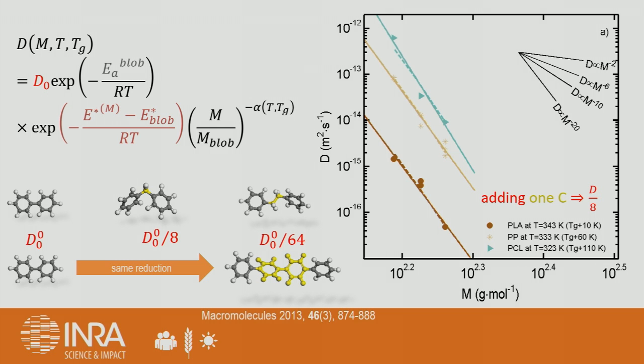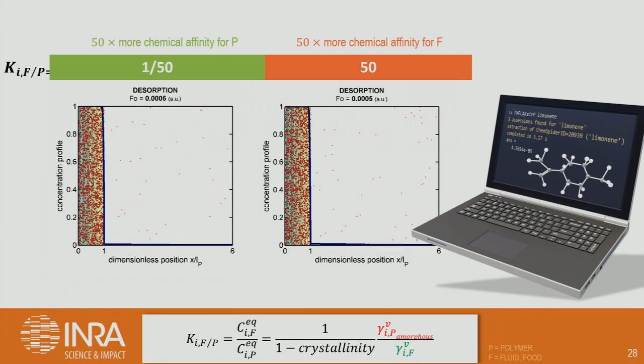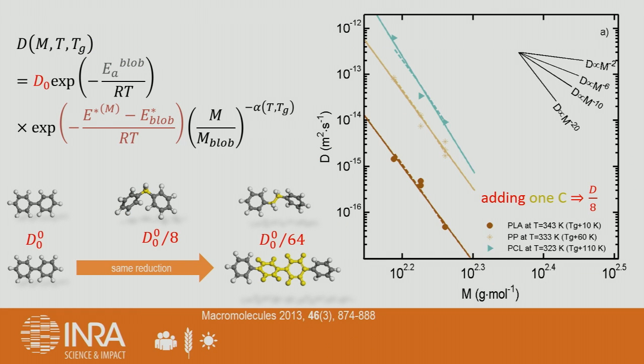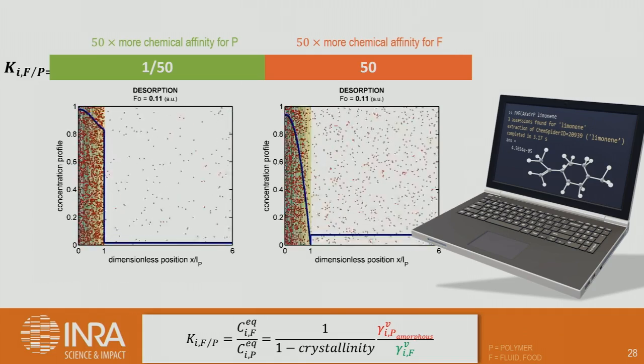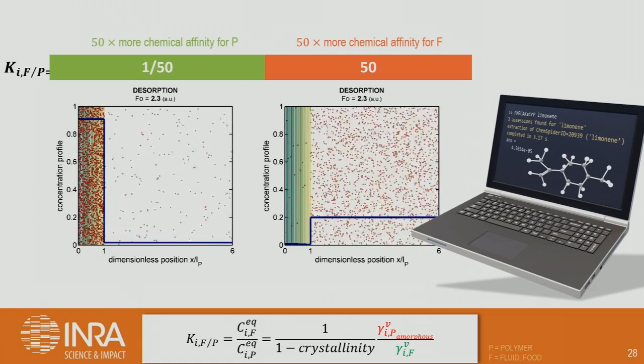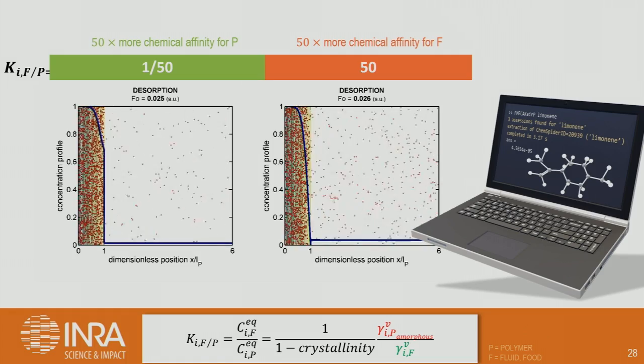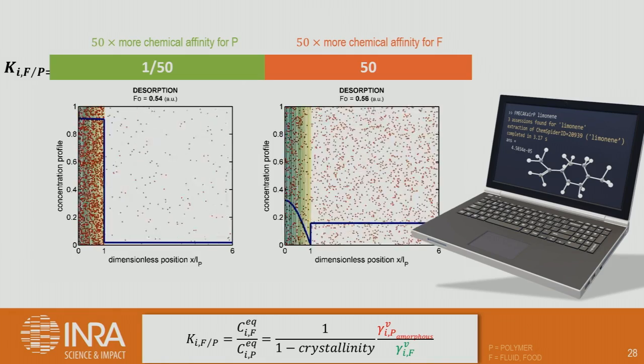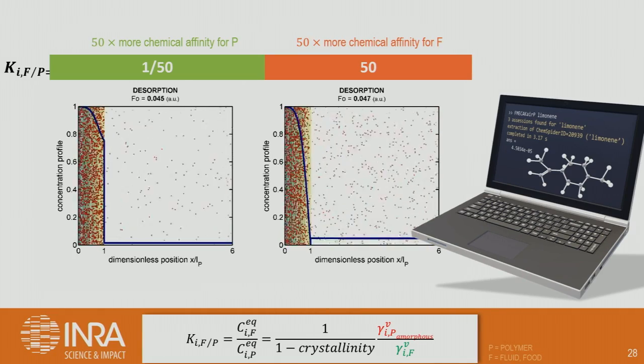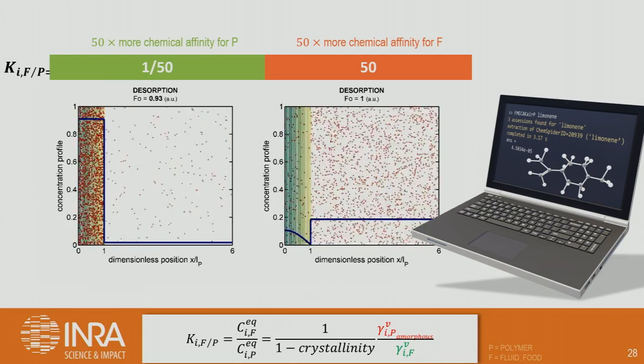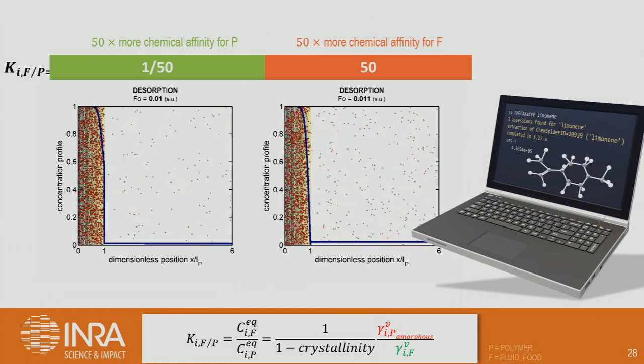With the previous procedure, to get the same reduction in diffusion coefficient you would need to double the size of the substance — for example, going from biphenyl to quaterphenyl divides the coefficient by 64. But you can achieve the same just by adding one carbon — adding flexible elements close to the center of mass of the solute. We can also use molecular modeling to assess chemical affinity. You can see here packaging and food for different chemical affinities: here the substance prefers to stay in the material, and here the substance prefers the food, almost completely emptying the material over time versus limited extraction.